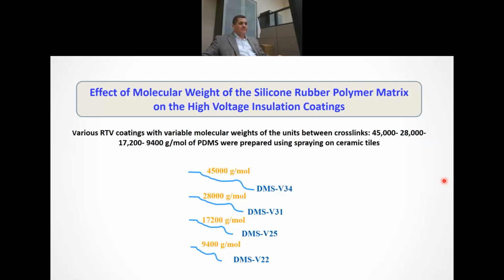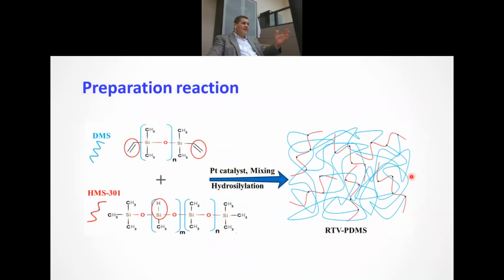We designed a system with four different molecular weights, which are very much available on a commercial scale from Gelest, the American company. We varied the molecular weight: 9,000, 17,000, 28,000, and 45,000. And we made the spray coating on ceramic tiles. This is the chemical reaction. As a chemist, you see we use polydimethylsiloxane. Different molecular weights have a different number of monomer units; the n will be different from one to another.